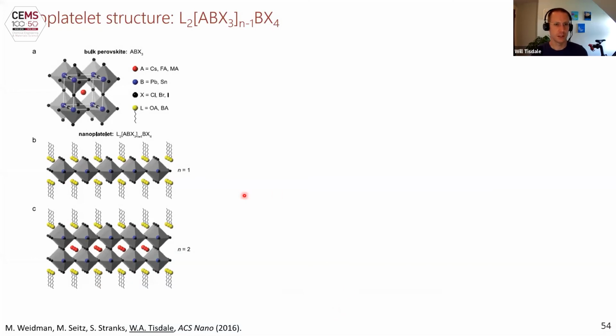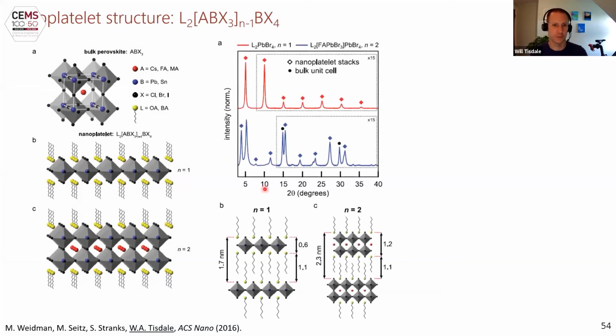The structures here, we can learn a lot about them from doing X-ray diffraction. If you drop cast that colloidal suspension onto a solid substrate, all the sheets lie flat on each other and stack, and you get well-defined interlayer diffraction peaks, as you can see here, that are periodically spaced that allow you to very accurately identify the thickness of the ligand layers and the thickness of the perovskite layers themselves.